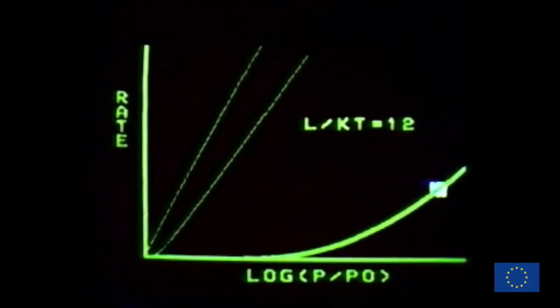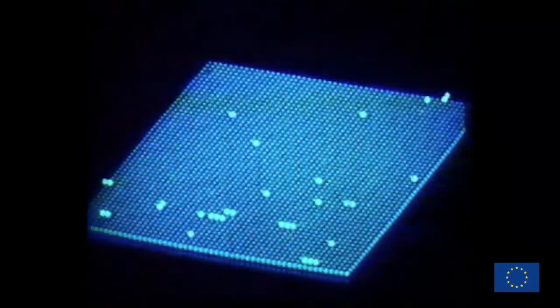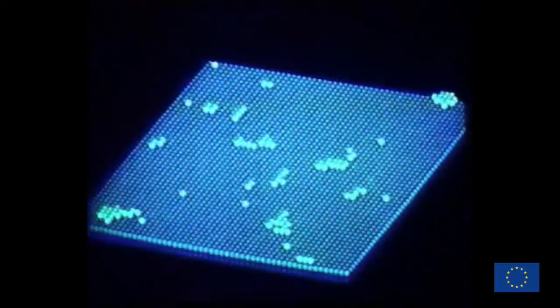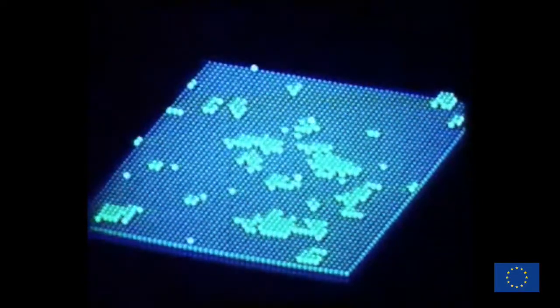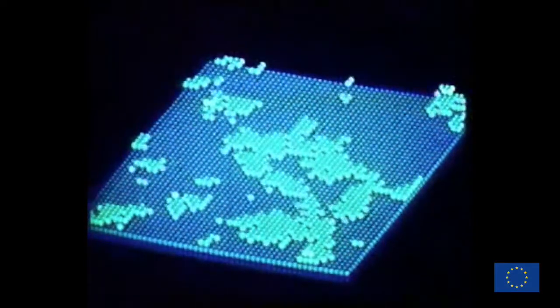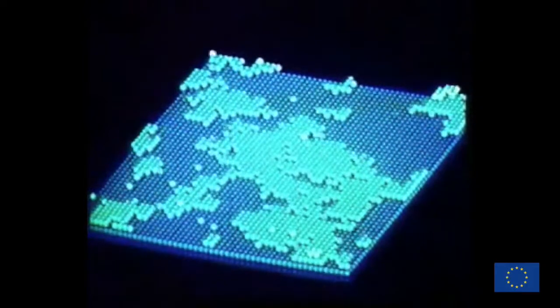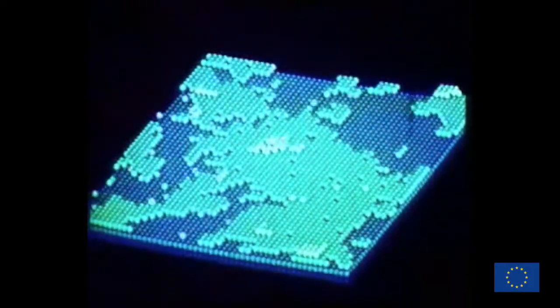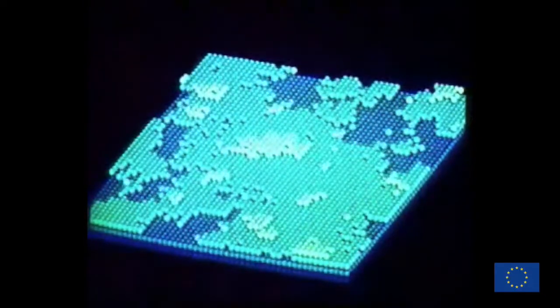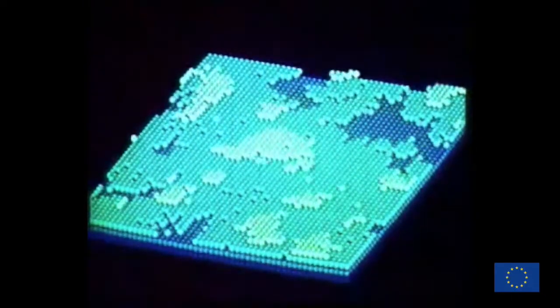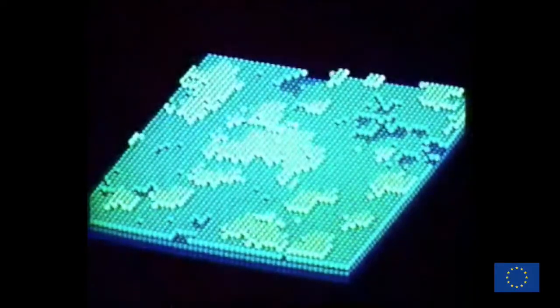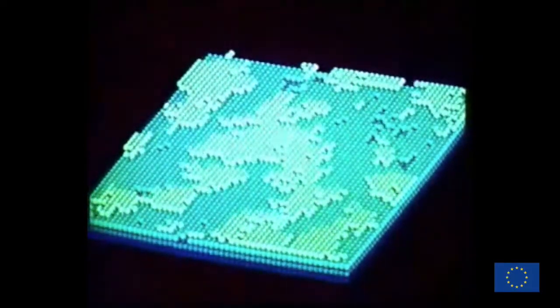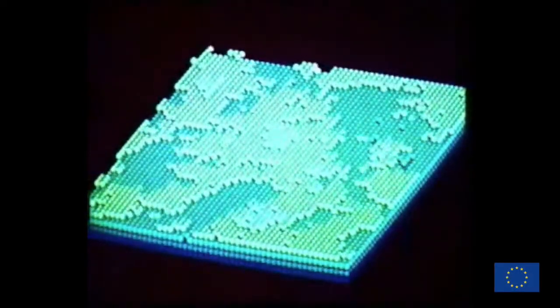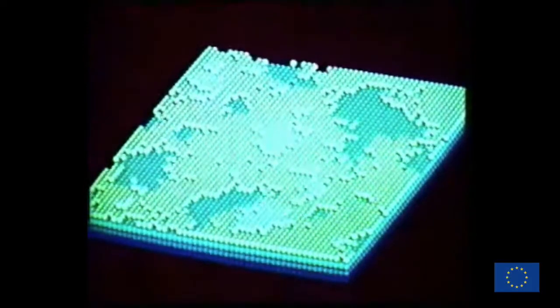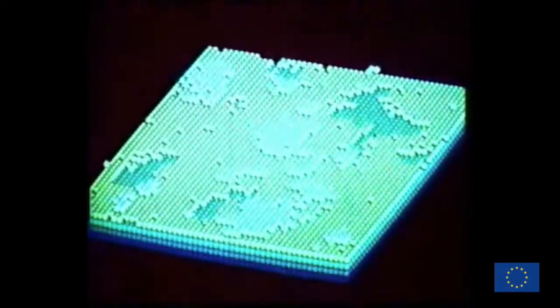Movie 2, we do the same, but we have much larger oversaturation. And so, one thing to notice is that the critical size of these islands now is much smaller. It is much easier for one of these small things to go into a large one. I think now the limit is about 5 atoms or something already. Of course, also because of larger oversaturation, your growth rate speeds up significantly. It's much faster than the one before. And the third aspect of this is that the roughness is worse than in the first case. So it is much easier to create a 3D surface. Okay, so that was the basic thing.